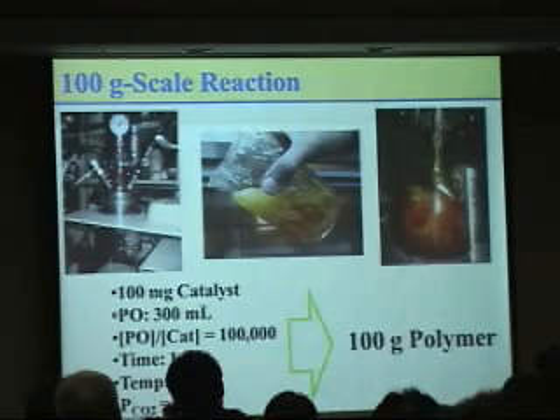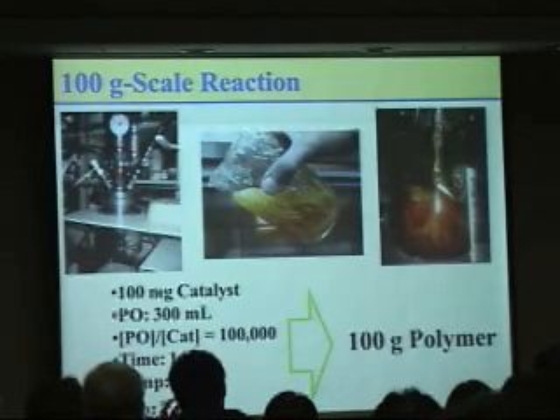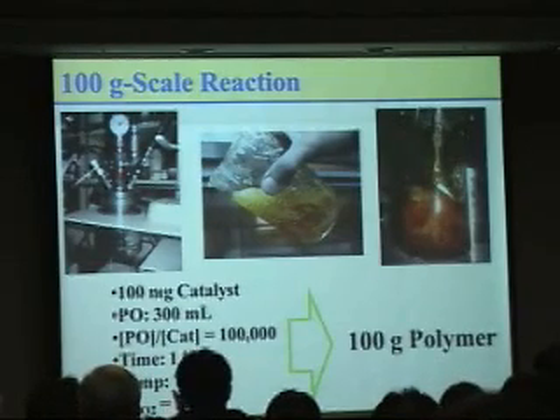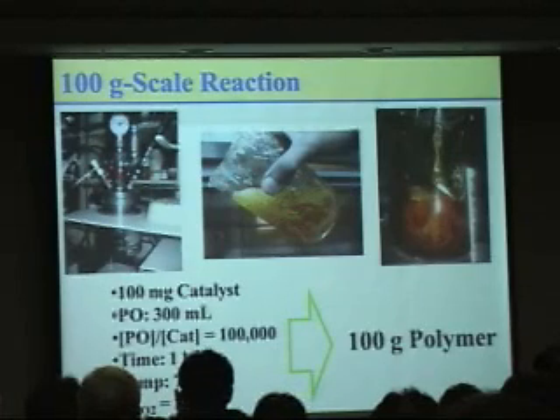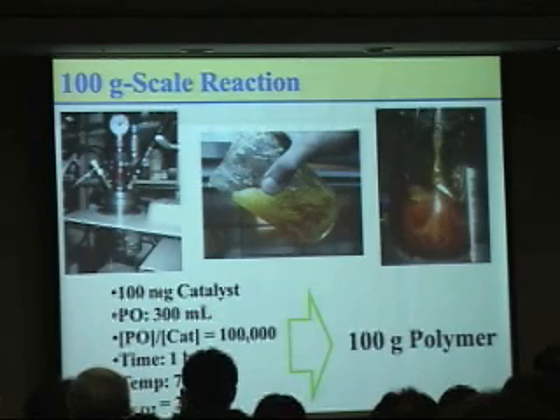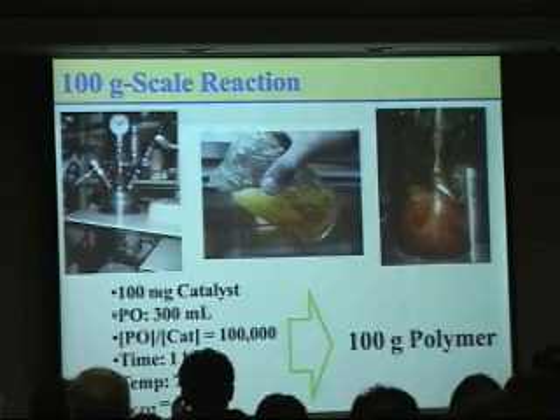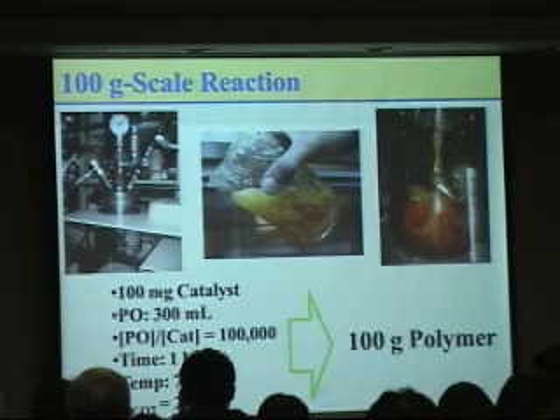So with a 500 milliliter reactor, we can make this kind of thick viscous polymerization by adding 100 milligrams of catalyst, using 300 milliliters of propylene oxide, by running just 1 hour at a temperature of 75 degrees C. So we can make 1 kilogram of polymer with 1 gram of catalyst just by running 1 hour.